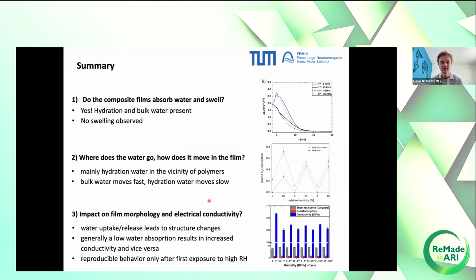And with this, I want to summarize the talk. So I asked a couple of questions in the beginning. Do the composite films absorb water? Clearly, yes, but they don't swell. We have a pretty good idea where the water goes. It's mainly present there as hydration water, not so much as bulk water. We also know in quite some detail how these water species move. The diffusion coefficient is dependent on the amount of water that is actually present.